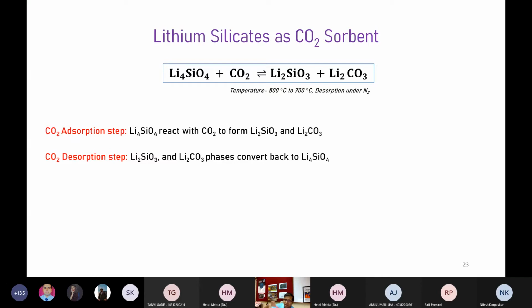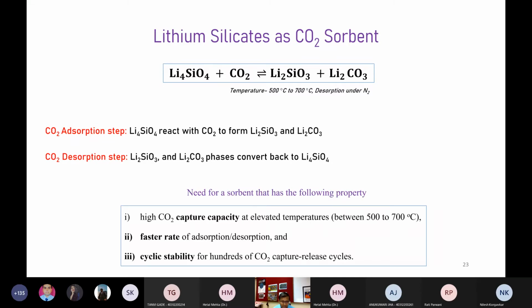But then once you capture, you want to take it and put it in a cylinder. You reverse the reaction by simply changing the gas to nitrogen at the same temperature. Then metasilicate and carbonate react together to get you lithium silicate, and the CO2 gas you capture into the cylinder. But because the reaction temperature is very high, most of the lithium silicate reported in the literature was not stable. Within a few cycles, even 2-3 cycles, they used to lose their capture capacity. So we wanted to make something better.